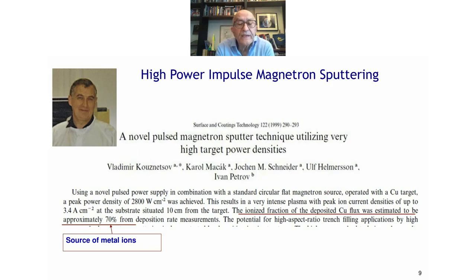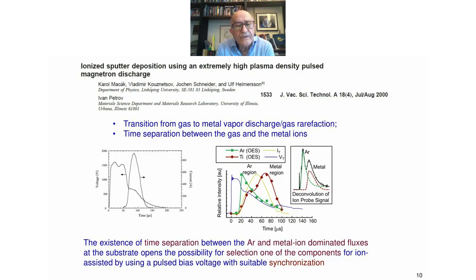Now, some 25 years ago, we introduced high power impulse magnetron sputtering. For the first paper, Vladimir Kuznetsov brought this power supply to Linköping, and in the group of Ulf Helmersson, we did some measurements of this discharge. What came out is that we can have peak current densities 3 orders of magnitude higher than in a conventional magnetron, and also that the ionized fraction is up to 70%. So the message was that this is a technique for producing metal ions. Next slide.